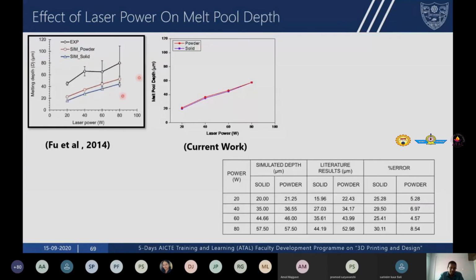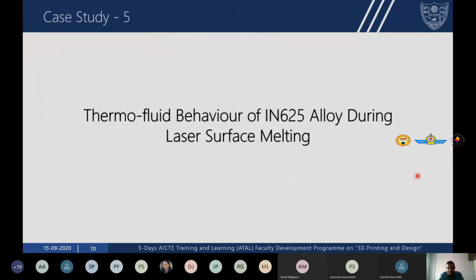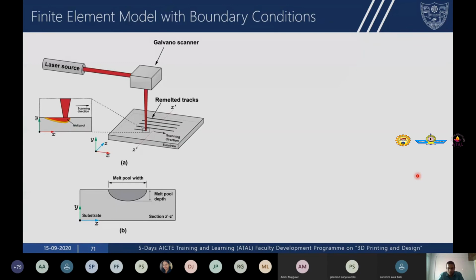This is for the melt pool depth. Again, blue is for the only-solid case, and red is for the solid and powder, and the same is done in our computational models. Again, these show good agreement between our predictions and their predictions of depth, and the percentage error is much lower for the width case. The last case I'm showing is when we consider fluid flow in the models. As I said earlier, heat transfer and fluid flow affect the shape of the molten pool, and they also affect the dimensions of the molten pool.